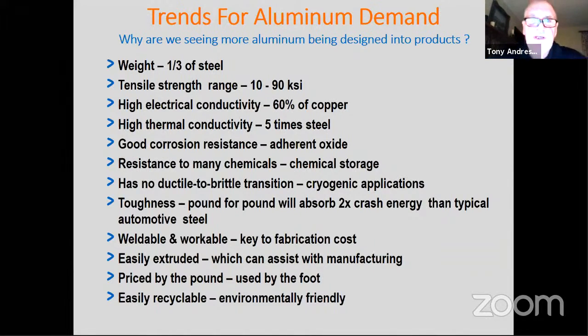High electrical conductivity, 60% of copper. So it has really good electrical conductivity, and it is used for that property in some applications. It's far cheaper than copper, and it's much lighter, obviously, than copper. So it can be used as an electrical conductivity media quite successfully. High thermal conductivity, 5 times that of steel. So it conducts heat 5 times faster than steel. Is that a good thing? Yeah, possibly, if you're using it as a heat sink or something like that.